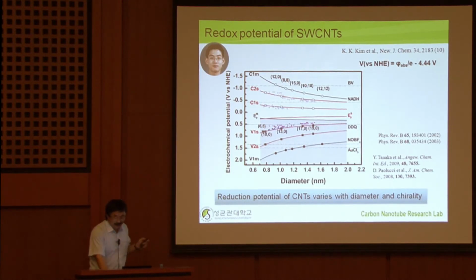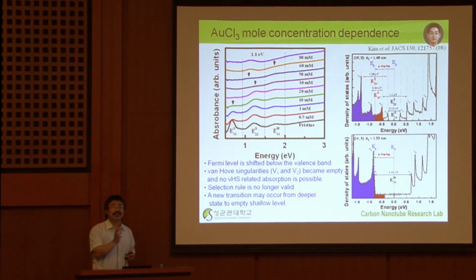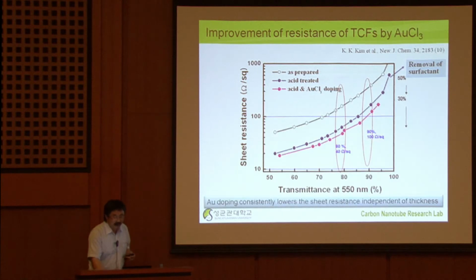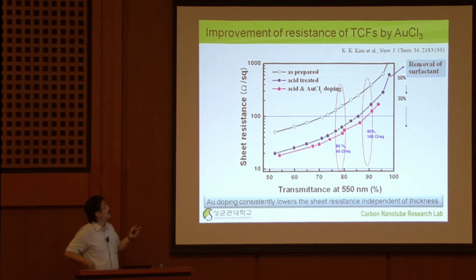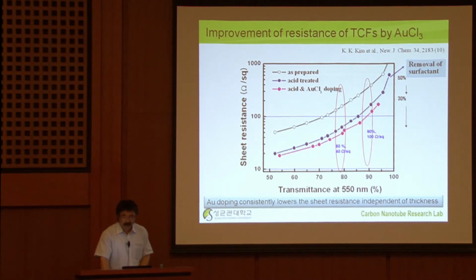Actually, I'm going to just skip this one, okay? But what we found, other than just a simple acid treatment, we actually had a further doping treatment. For instance, using gold chloride, we are able to dope the carbon nanotubes and then improve the conductivity further. So this is the result. For instance, after this acid treatment, we further treat this by gold chloride, you see the improvement of the sheet resistance again, at least about 30% for each case. So with this kind of improvement, we can now use this film for touch panel, even for some small size display applications. Actually, we have one Korean project working together to develop this film now for real application of touch panel.